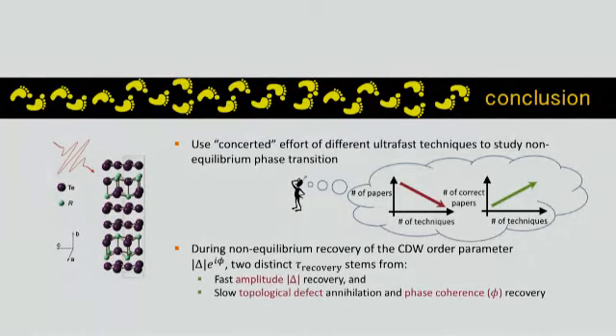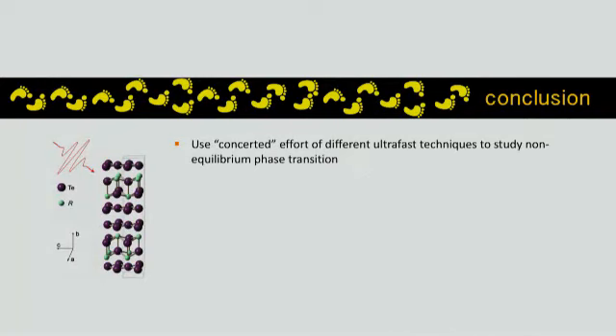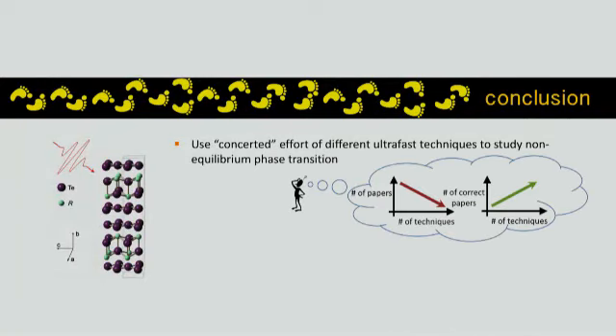Can you say something about the size of the domains? And also, if it's a longer time scale, is it possible that it's a power law and not an exponential? That's a good question. For the size of the domain, we can estimate from the width of the CDW peak. But there's one problem: we need to characterize, for example, the instrument resolution. We estimated that for this particular peak width, the domain size is a few unit cells.